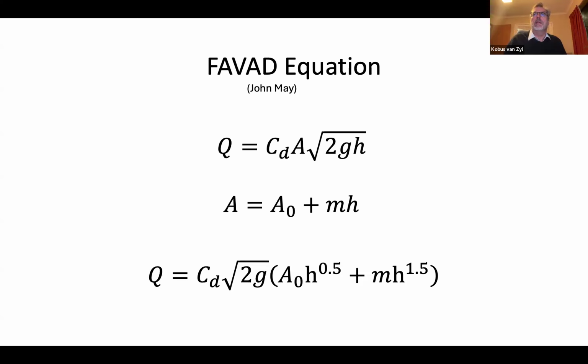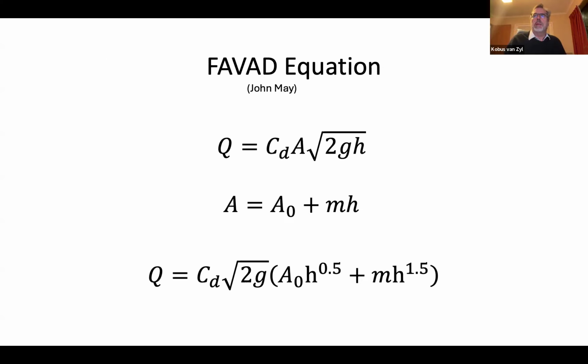But anyway, so this is the FAVAD equation of flow rate. And it's important because the flow rate determines when you can find a leak. So if you have a longitudinal crack that opens up with pressure, you're going to find that crack at a lower pressure than you would a round hole with the same area.